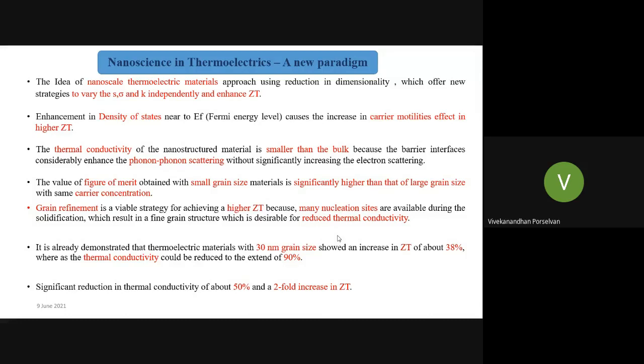The mean free path is getting reduced. Okay, as the mean free path is getting reduced, what will happen? The electrical conductivity is reduced. In order to achieve higher electrical conductivity in a material, we should have a higher carrier concentration, which means the holes or the electrons, and those holes or electrons should move in a 3D bulk material with a higher mean free path. So the distance traveled between two scattering centers should be more, thereby we can achieve higher electrical conductivity. So that is what we need.